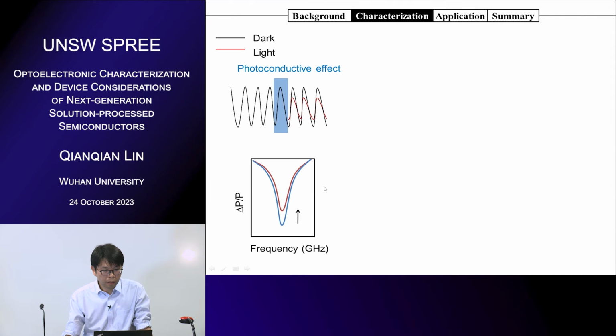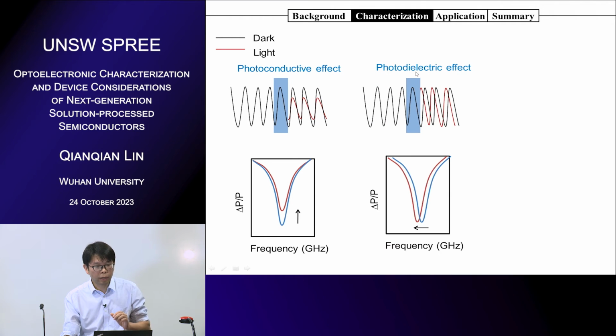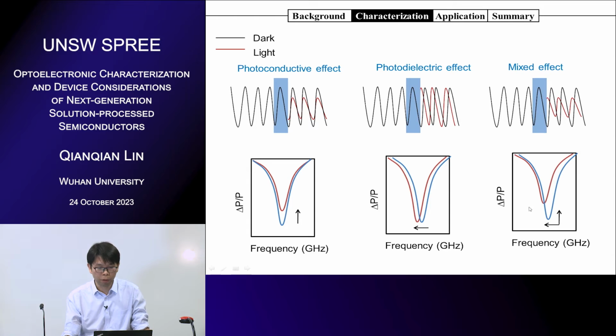Because under the photo excitation, we look at the state in dark and under illumination. So it can have photoconductive effects, so the amplitude changed under illumination. And we can also have photodielectric effects, so the phase shifted, but the amplitude didn't change. Normally we have the mixed effect, so we have both a change of phase and also amplitude.